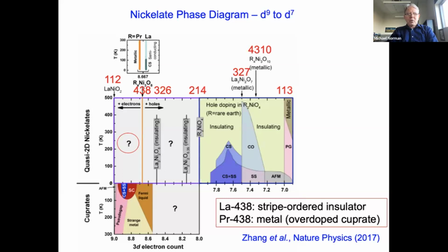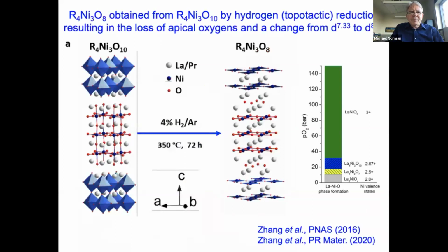This is something that we started working on in 2015. Of course, you get these line phases, and of particular interest is the 438, which is the reduced variant of the 4310, where the lanthanum compound was a stripe-ordered insulator, but the praseodymium compound was a metal, and in fact its transport properties look very reminiscent of overdoped cuprates. The way this happens is that one uses hydrogen, called topotactic reduction, to strip out the apical oxygens of the material. In the trilayer case, this leads to 438.